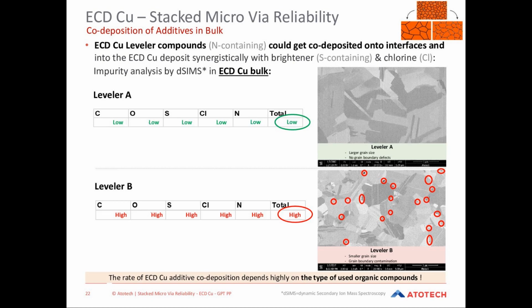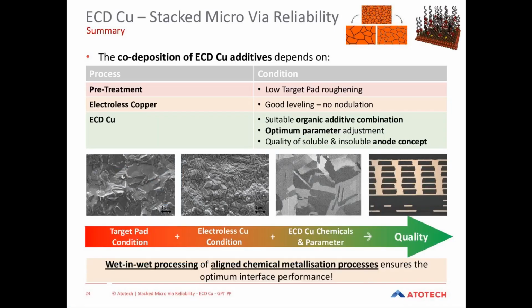So this is only an example of some of our studies we have done in this regard and our findings. Here now a summary for you. The main takeaways of this short introduction to stacked via reliability is that starting with a target pad area, which needs to be, of course, clean, but should not be roughened too much, followed by electroless copper processes, which are not tending to create nodulation on such target pads to keep the growth sites and the number of growth sites very low for the absorption of the additives.